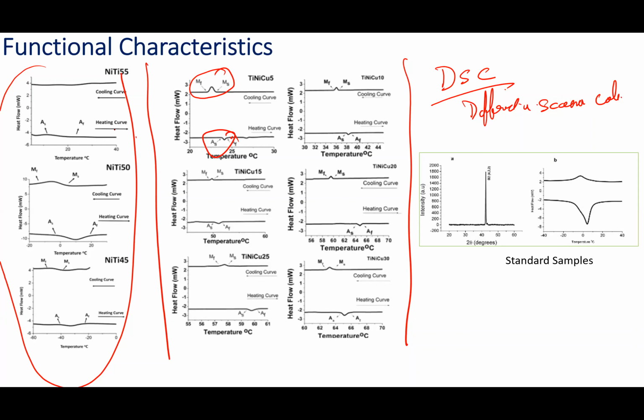So with respect to variation in composition, we could understand the phase transformation. This is the phase transformation we observe with the conventionally available sample, which confirms the formation of a proper beta phase, and this also confirms the transformation from austenite to martensite. Similar observations were made with respect to the additive manufactured sample.